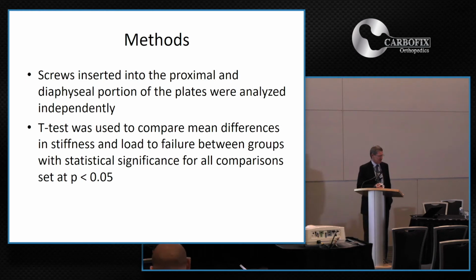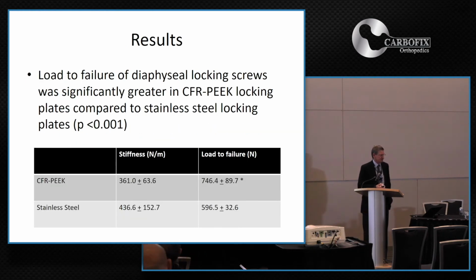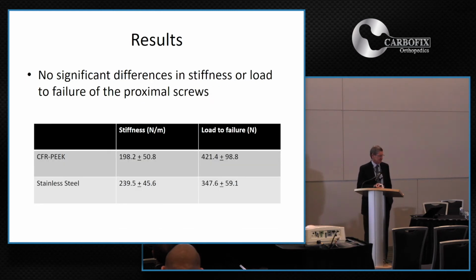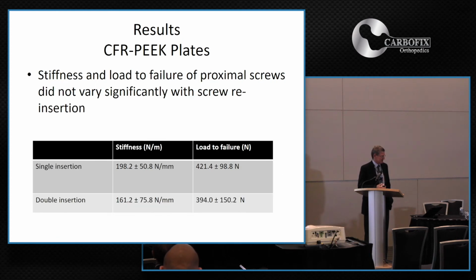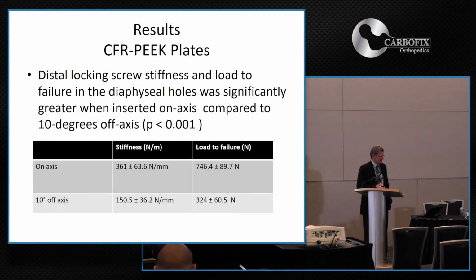A t-test was used to compare the means, and the result was that the load to failure in the diaphyseal locking screws was significantly greater in the CFR PEEK plates compared to stainless steel, and the values are shown here. There was no significant difference in the stiffness or load of the proximal screws, so equivalent. And stiffness and load did not vary significantly with this screw reinsertion. The distal locking screw stiffness and load to failure in the diaphyseal holes was significantly better when it was inserted on axis compared to the 10-degree off axis, which is what we've seen in other plating systems.